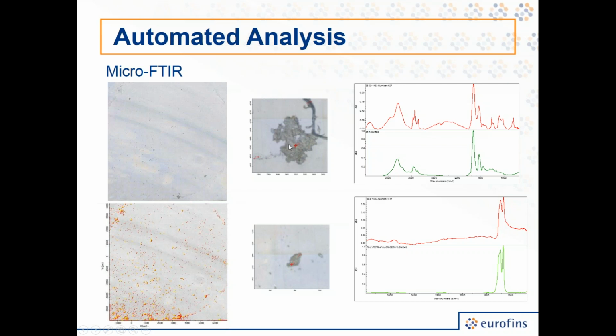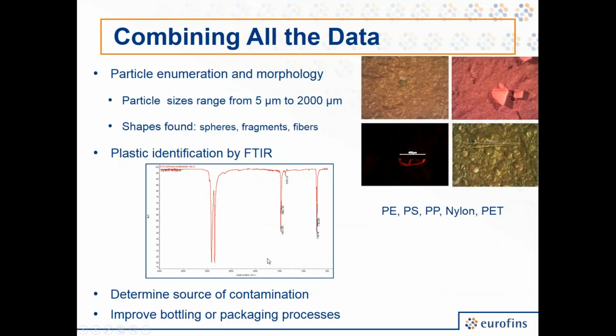We can do microscopy, so we can get a magnified image, determine sizes, and then for each particle, we can do a spectral scan. And then these systems also have libraries of spectra, so we can do comparisons to our library data and then come up with a match. And so in the end, when we're providing someone with data, we provide them with actually quite a bit of information. We come up with particle counts and morphologies. So literally we can show them images of what we found, spheres or fragments, fibers like this, branched fibers, or even linear fibers as such.